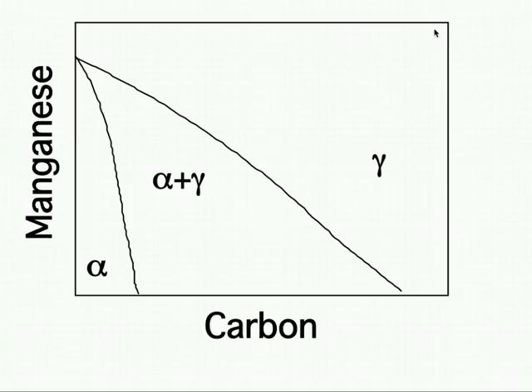Now, there will come a temperature where the manganese atoms are no longer able to partition at all. In other words, the manganese to iron ratio in the ferrite will remain the same as the manganese to iron ratio in the austenite. So we actually lose equilibrium because the manganese is not partitioning, but the carbon still has a very high diffusion coefficient and therefore is able to partition between the austenite and the ferrite.